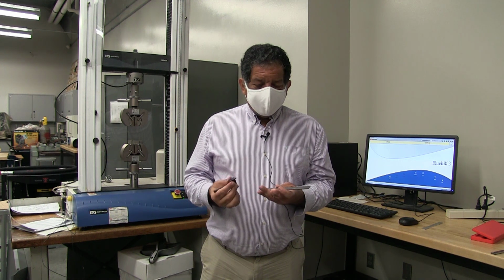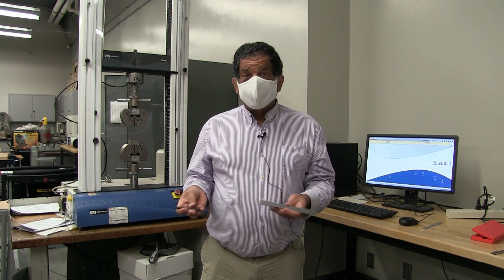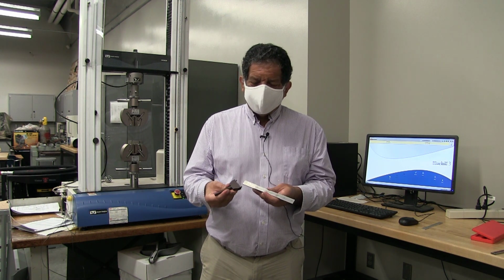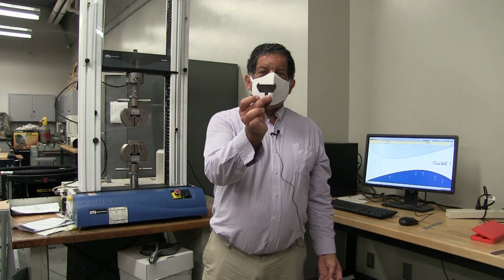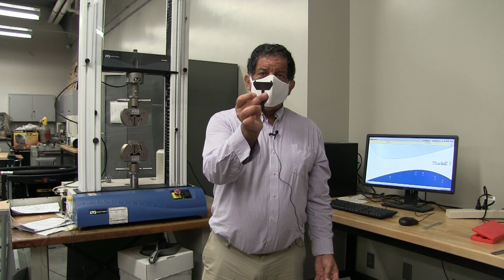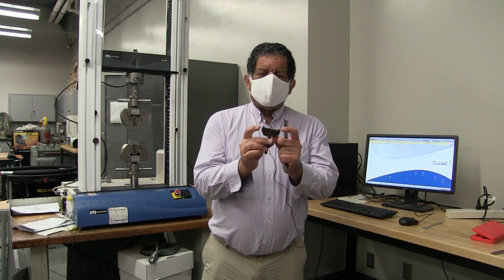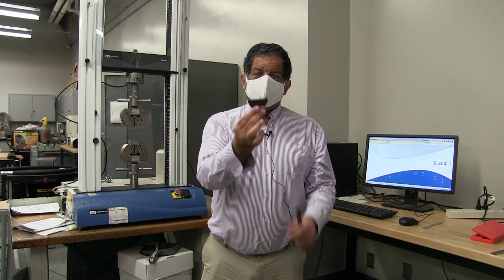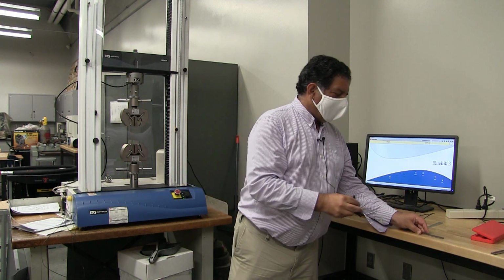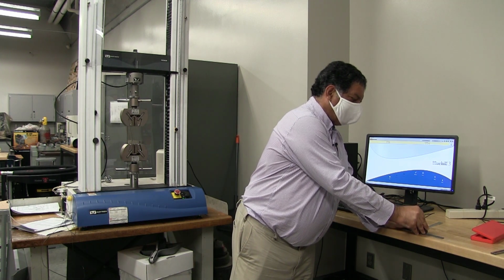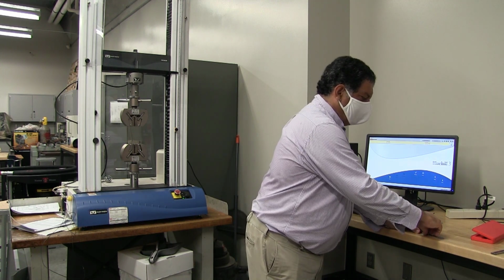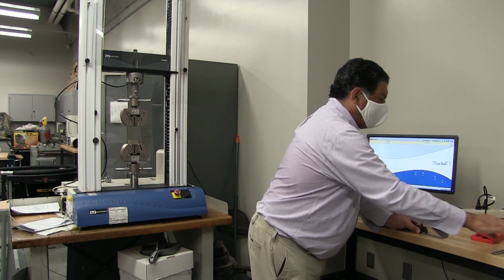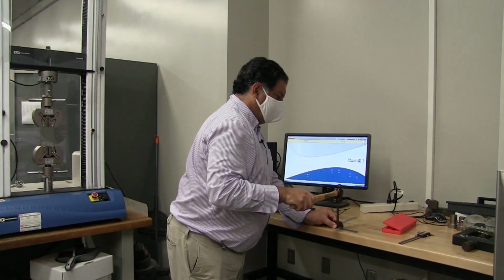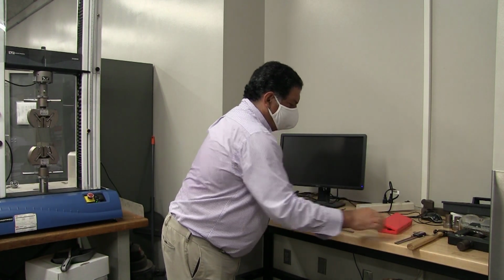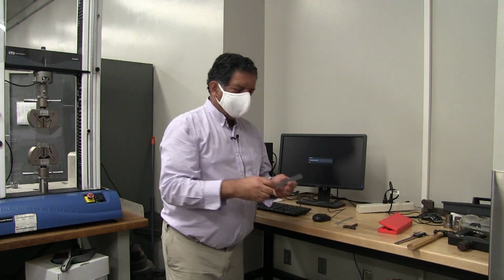A third alternative for measuring percent elongation, and this is something that people typically do during tensile tests, is to take a pair of punches which have a separation of exactly 2 inches, like this, and then you put it on your specimen in the center of your specimen, and then you whack the center of the specimen with a hammer in order to put 2 little indentations on the specimen.